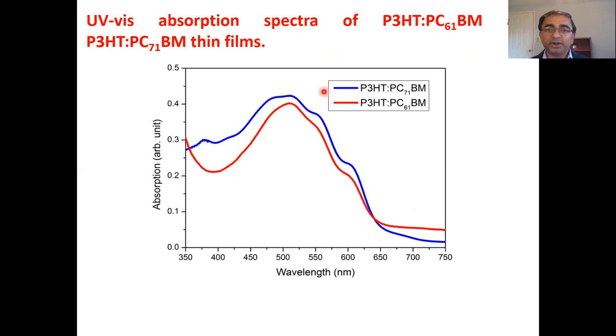And when I replaced it, I made thin films, and you can see this blue part and this red part. This is with 61, this is with 71. And I found that with 71, we have an enhanced absorption spectrum. When you enhance the absorption spectrum, you increase the absorption, so you will absorb more energy. So the PC71BM organic solar cell will absorb more photovoltaic energy than the P3HT:PC61BM solar cells.